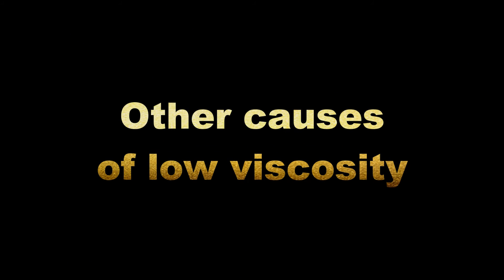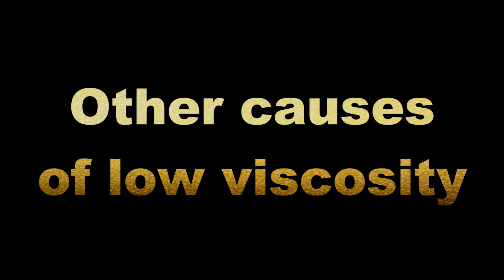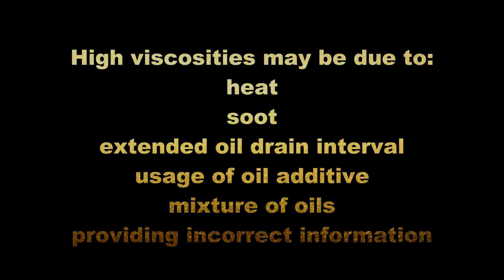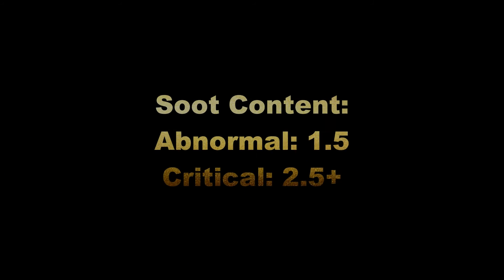A low viscosity result may also indicate a mixture of different oil grades, or be the result of reporting the wrong viscosity grade to the laboratory. A result which is higher than the acceptable specification may be an indicator of exposure to heat, presence of high quantities of soot, an extended oil drain interval, usage of an oil additive, and also may indicate a mixture of different oil grades, or be the result of reporting the wrong viscosity grade to the laboratory.